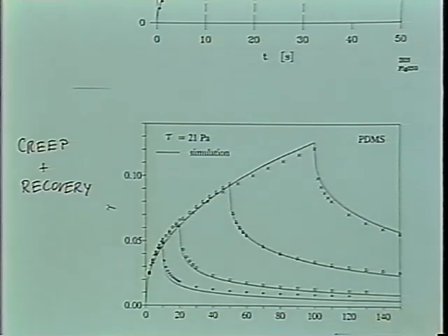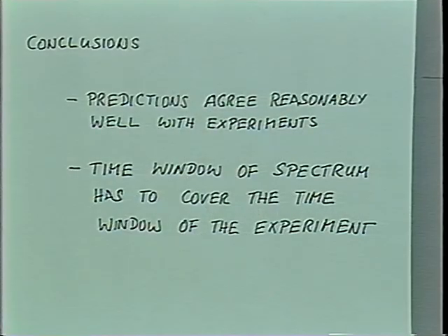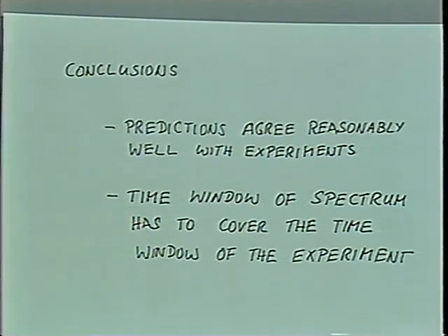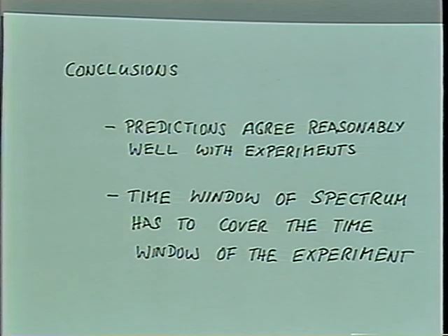We just looked at G prime, G double prime of those three samples, got the distinct relaxation modes, not caring whether it's a liquid or solid. Or in our window, we just got the representative modes, and we are using those in the modeling. Now you can see that the predictions are visible. If I sum this up, it's pretty good agreement between experiments and the predictions from dynamic mechanical data. And see, that's not bad. You're doing a dynamic mechanical experiment, and you're predicting startups and all kinds of other functions.